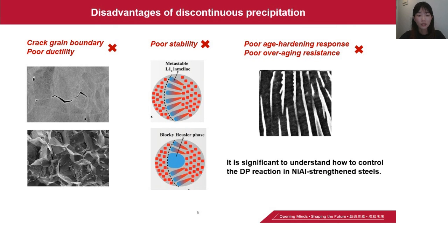Discontinuous precipitation is of great interest because it generally has a deleterious effect on the mechanical properties, such as poor ductility, poor stability, and poor overaging resistance. So it is significant to understand how to control the DP reaction in nickel-aluminum strengthened steels, and most studies focus on the CP reaction. Research on the DP reaction is very limited.